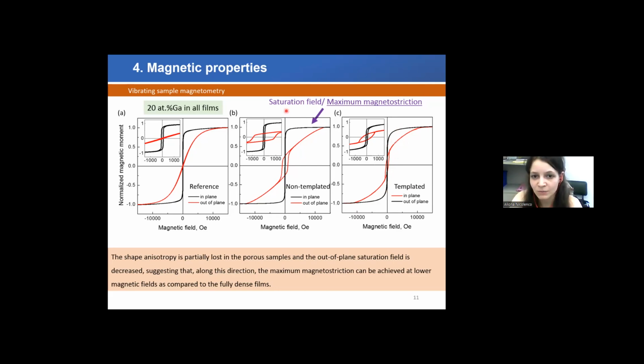For us, what is important to see is the saturation field, whether the porosity changes the saturation field of the films, because this is where the maximum magnetostriction can be obtained. At this field, all the domains are oriented with the magnetic field. We can indeed observe that the nanoporosity decreases the saturation field slightly as compared to the fully dense replica sample. In other words, that means that we can induce the maximum magnetostriction in this film applying smaller magnetic fields.